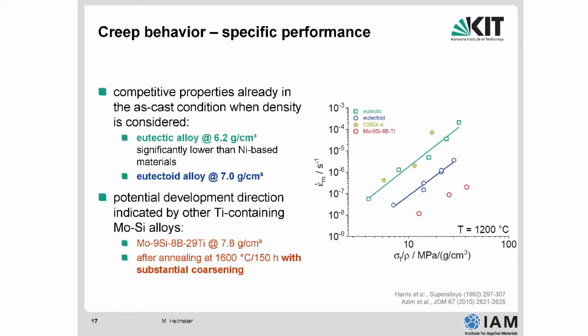Okay, then of course it all comes down to density. So I plotted here the specific strength: sigma, the stress level, the centrifugal load, over density versus strain rate. And what you see here is that indeed our alloys are already as good as the CMSX4 at 1200 C or even better. So here are data points for the nickel-based single crystal alloy, and our material, the eutectic, and other material with some additional amount of boron are much better. So we do have potential for being superior to nickel-based superalloys, for being able to replace them in high-temperature environments.